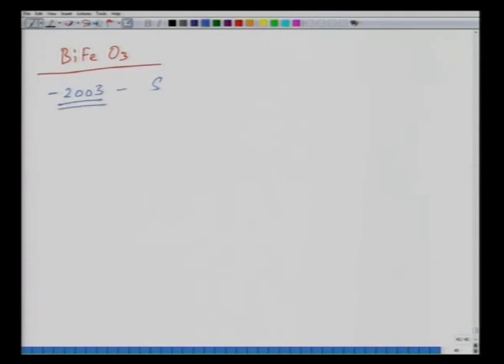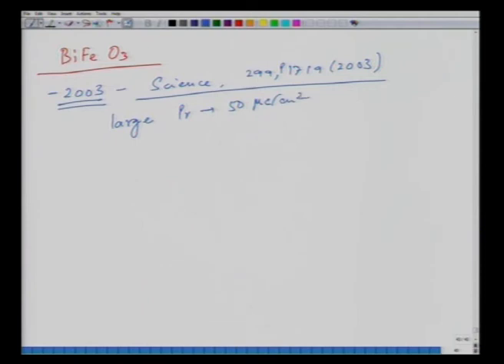So we will start with BiFeO3, which is also called bismuth iron oxide or bismuth ferrite. Now this is one of the most studied ferroelectric multiferroic materials. Earlier BiFeO3 was of course discovered by a lot of Russians in the 50s and 60s, but 2003 marked the year when a paper in Science, volume 299, page 1719, 2003, sparked massive interest in this material because the material showed large polarization of about 50 microcoulomb per centimeter square and magnetization.